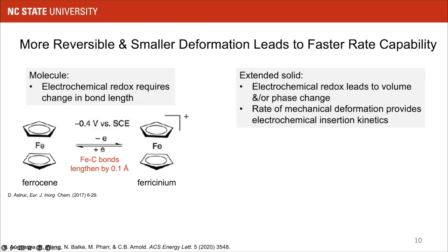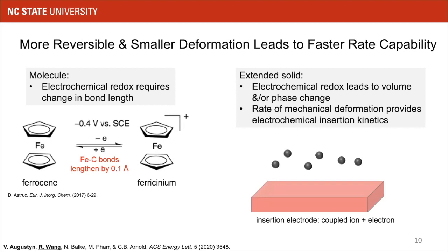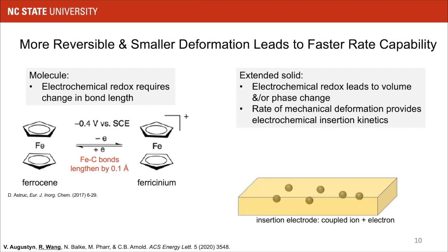First, I just want to make this note that there's a strong coupling between the mechanical deformation of a material or a molecule and rate capability. We know that electrochemical redox requires a change in bond length. So when ferrocene is oxidized to ferrocenium, one way that you could characterize that is because the iron-carbon bonds will lengthen. In an extended solid, these electrochemical redox reactions lead to volume and/or phase changes.